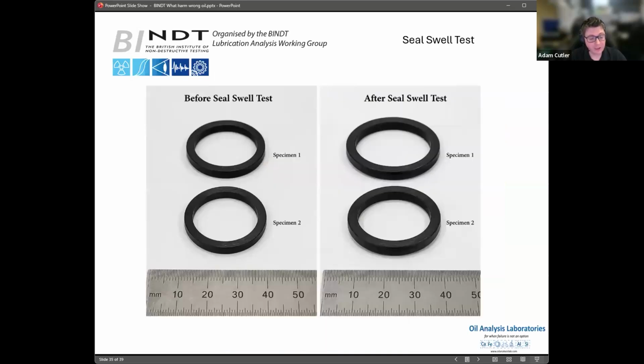You can also do direct specimen testing. So you can take one of the seals and you can take the old oil and you can take the new oil and see how the swell effects would be on that specimen. So we can see here we've got two equally sized specimens here. Now this one you can see is very slightly bigger than this one at the bottom. So you can see this is actually swollen a little bit more. Now, if we wanted it to be like this one, they would have gaps here because we're not getting enough swell. Or if it was vice versa, we wanted to have this one, and this is what the alternative product is, it could overswell and lead to, again, disruption of the seal.